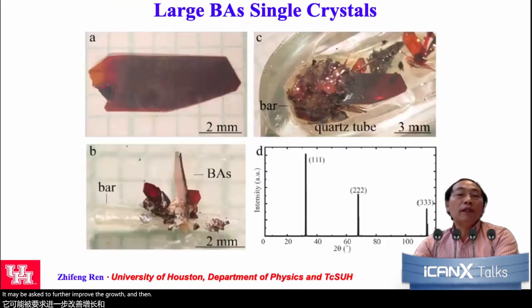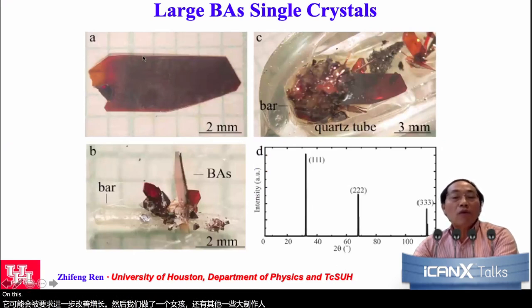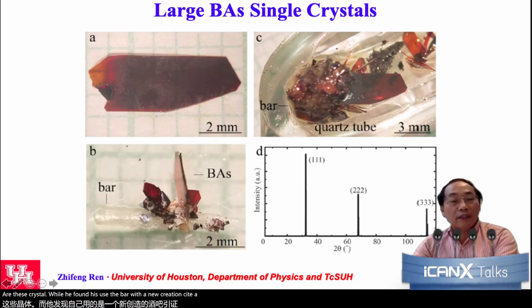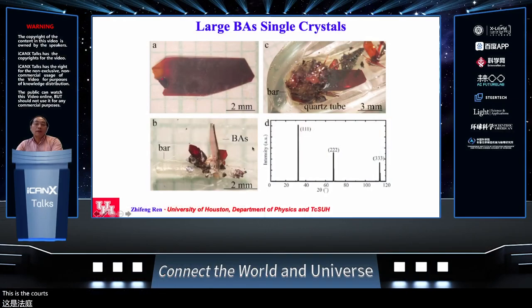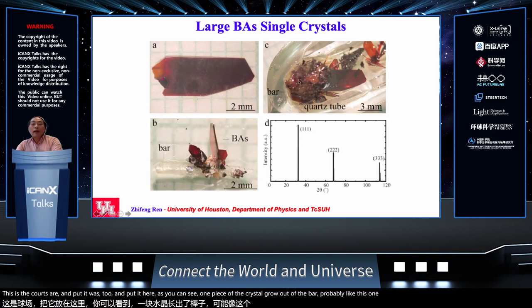And then we did grow some other bigger crystals. For this crystal, what we found is to use a bar with a nucleation site as a seed. This is a quartz bar, and we put it in a quartz tube and put it here. As you can see, one piece of the crystal grows out of the bar, probably like this one, and then